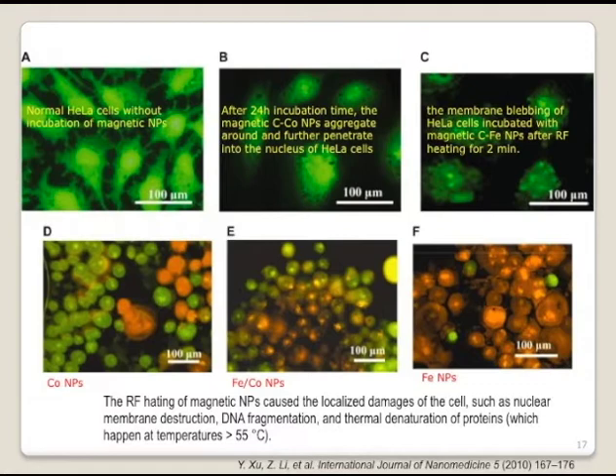We also see some differences. Why are some cells still alive and some not? That's because more nanoparticles entered those cells, which causes them to die. So this gives some information. Nanoparticles kill the cancer cells not because they raise the whole cell temperature very high. Actually, it is due to localized heating. Only at the site of the nanoparticle can the temperature rise very high, usually to 90 Celsius. This is higher than the temperature the cancer cell can stand. So this is the RF heating.